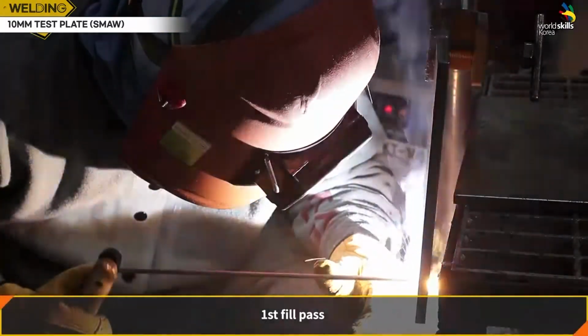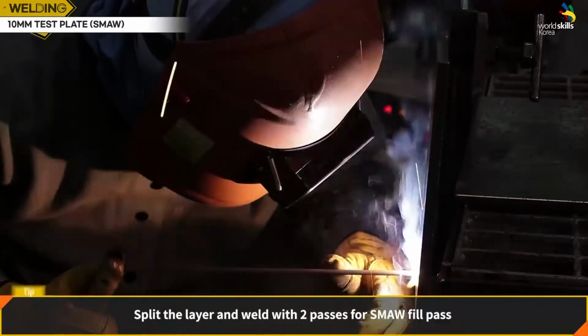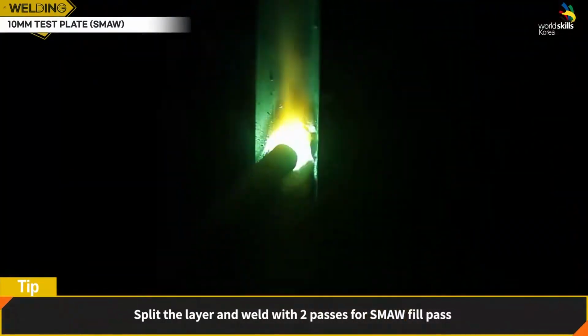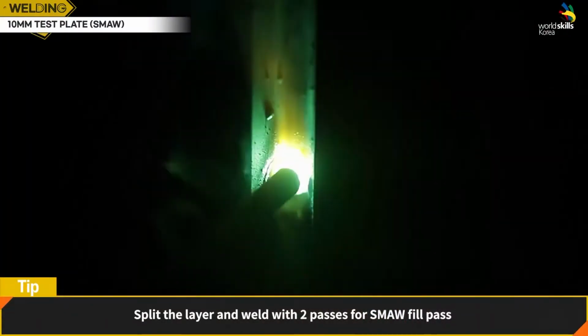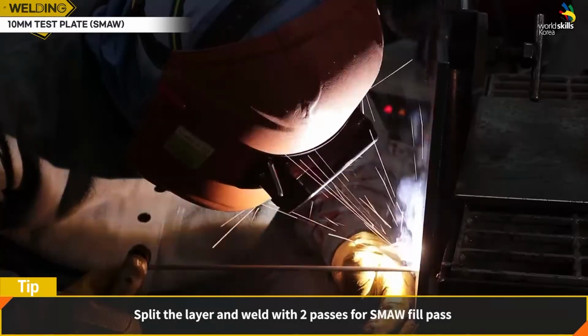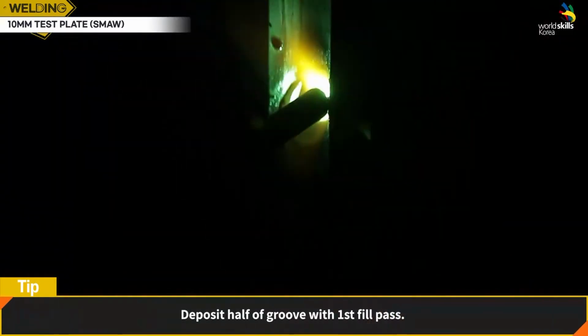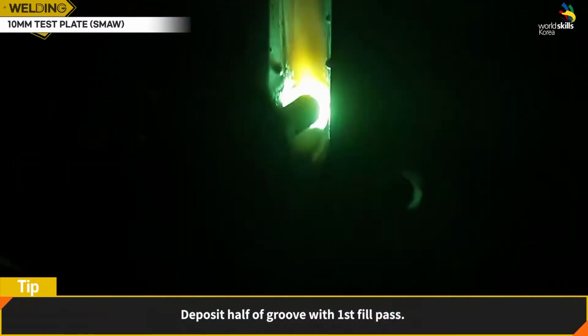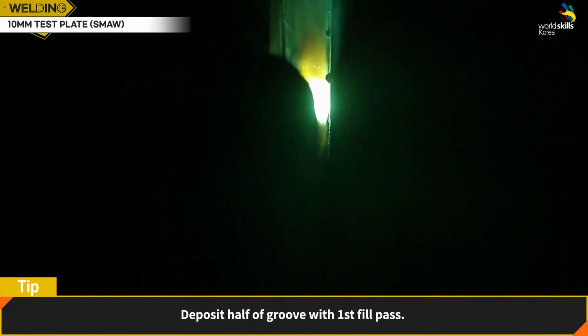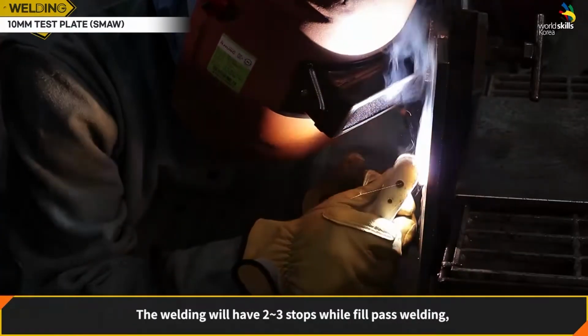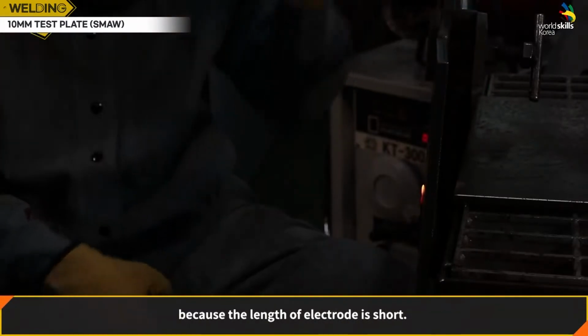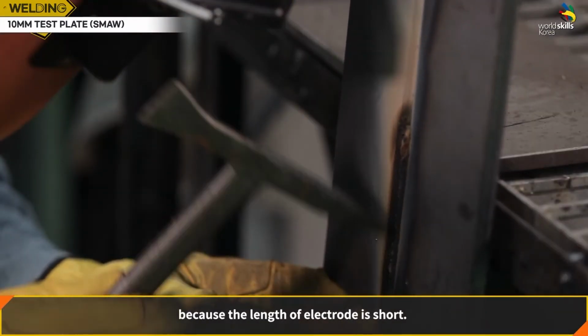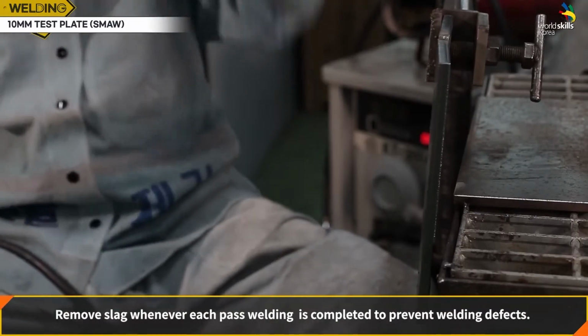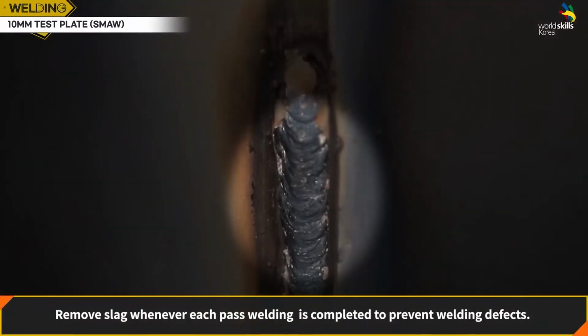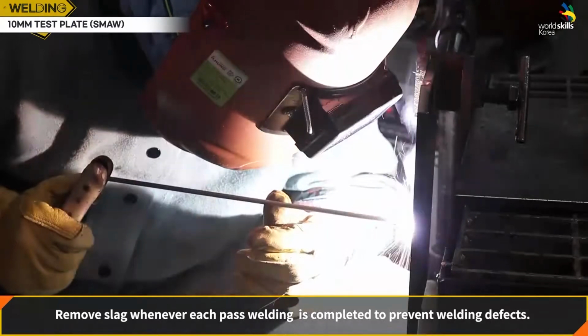Base material welding. Fill pass. Split the layer and weld with 2 passes for the SMAW fill pass. Deposit half of the groove with the first fill pass. The welding will have 2 to 3 stops during fill pass welding because the length of the electrode is short. Remove slag whenever each pass is completed to prevent welding defects.